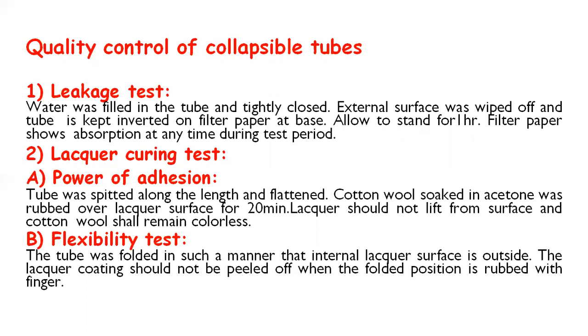Lacquer curing test. Power of adhesion. The tube was slit along the length and flattened. Cotton wool soaked in acetone was rubbed over the lacquer surface for 20 minutes. Lacquer should not lift from the surface and cotton wool shall remain colorless. Flexibility test. The tube was folded in such a manner that the internal lacquer surface is outside. The lacquer coating should not be peeled off when the folded position is rubbed with finger.